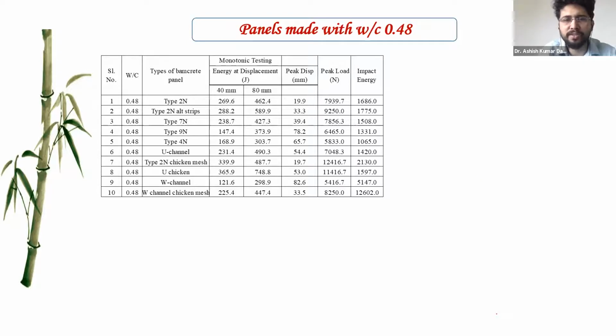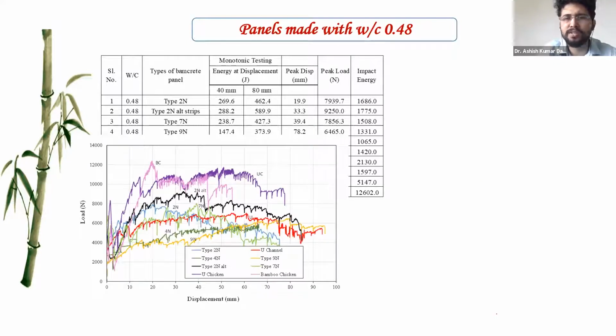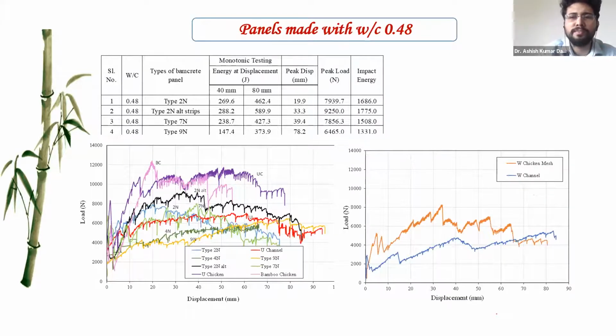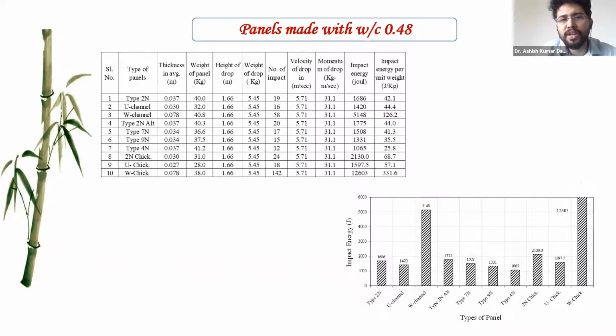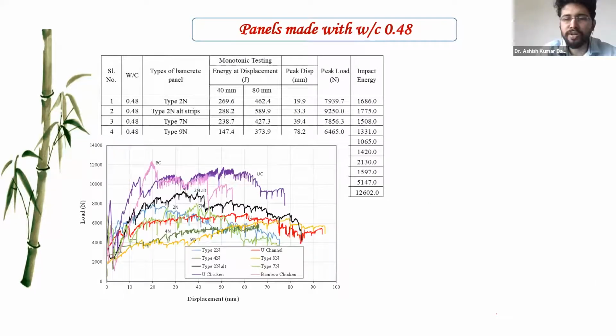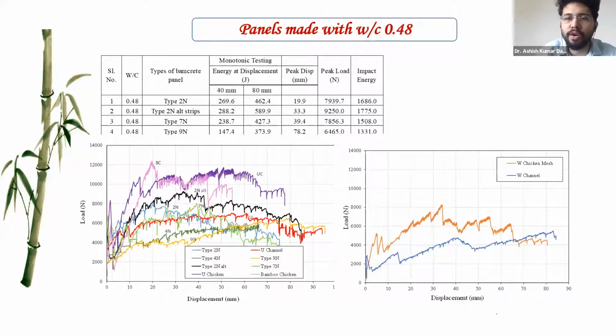After that, we especially chose the 0.48 water cement ratio, and different panels were cast. These are their monotonic loading results. It was found that the twin bamboo mesh panels were very high, about 12,603 joules of impact energy absorption, compared to the single mesh concrete walling system. But in the monotonic loading, the twin mesh system showed a much lower level of energy compared to the single concrete panel mesh system, because of the mortar which is not interconnected from one side to the other side. This might be the reason.